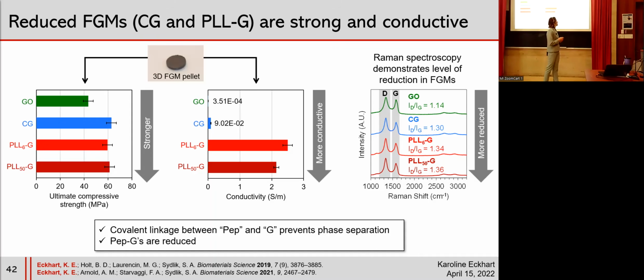And we can see that the trends seen in the intensity of the D to G band correlate to those in the ultimate compressive strength and the conductivity, suggesting that the level of reduction of these FGMs is a really important feature in enabling them to have good material properties for a regenerative scaffold application.